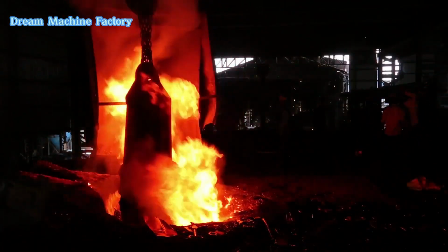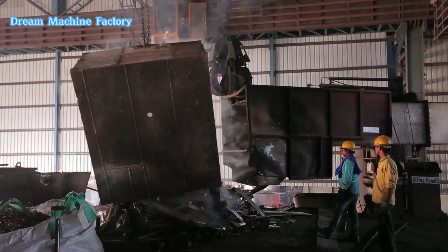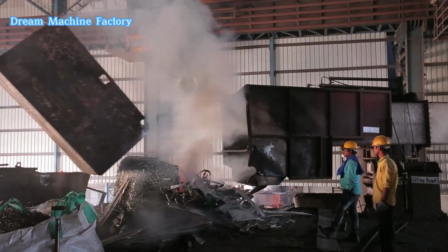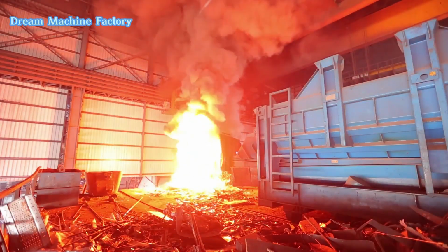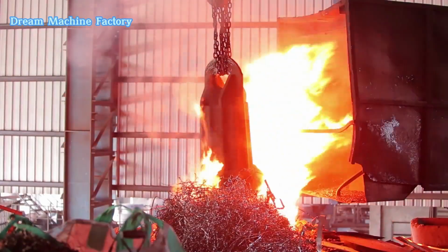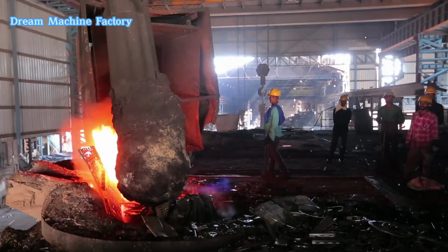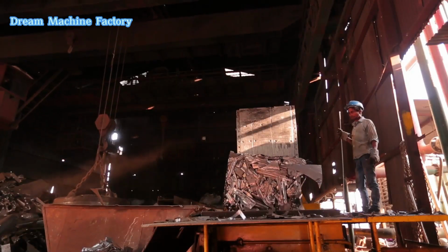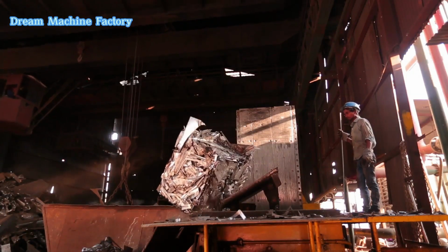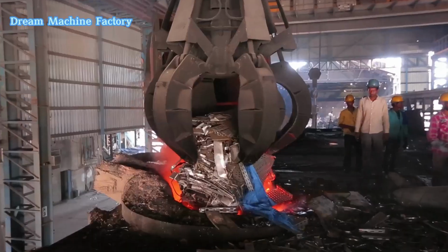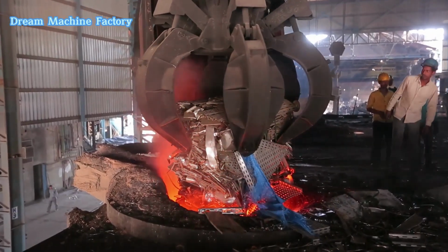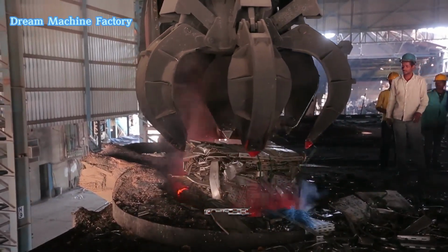Processed scrap offers numerous advantages, including a faster melt rate, reduced slag generation, extended furnace lining life, and reduced air pollution. For example, using 40% processed scrap in a 10-ton furnace can reduce heat cycle time by 10% and energy consumption by 5%, leading to significant savings.